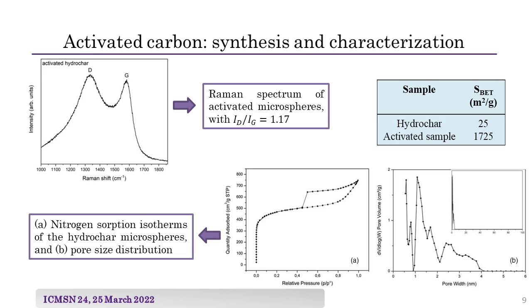However, the specific surface area value is not the only aspect to be considered to assess porous carbon materials as potential electrodes in supercapacitors. A crucial role is played by the pore size distribution, which must exhibit both micropores to maximize the amount of charge and then the energy density, and mesopores to facilitate the flux of electrolyte ions, increasing the power density. The activated carbon microspheres obtained in this work have a high density of micropores, as demonstrated by the pore size distribution in Figure B, and a mesopore structure clearly observed in the same curve, which gives rise to the typical hysteresis in the isotherm in Figure A.